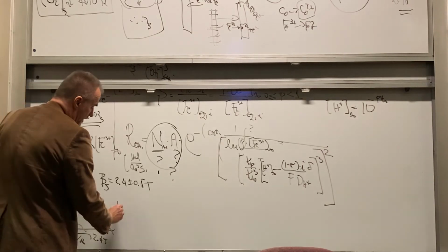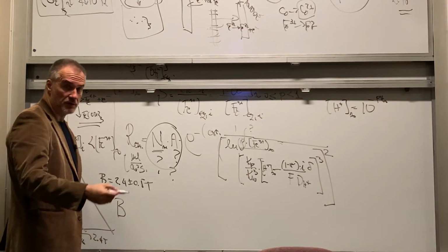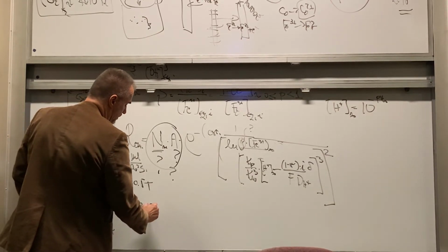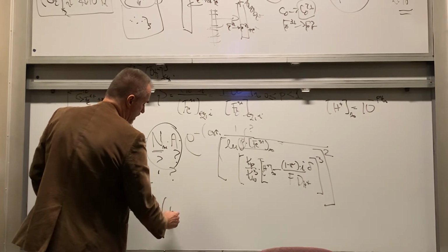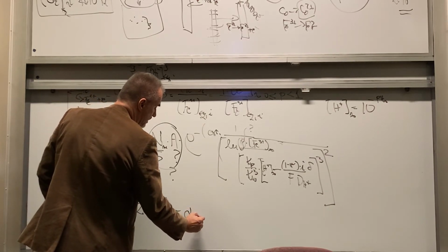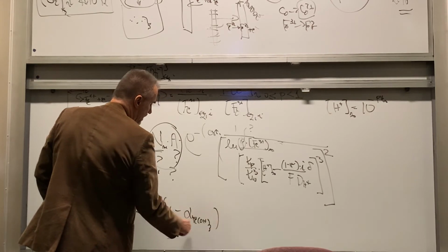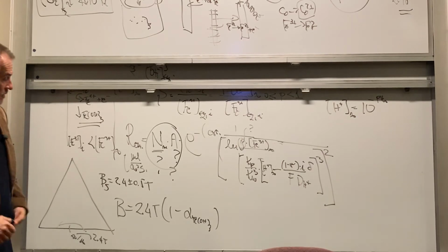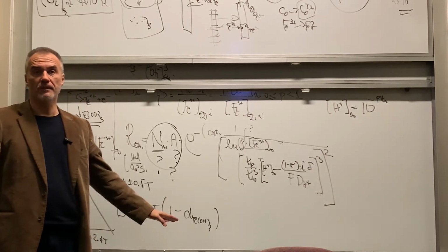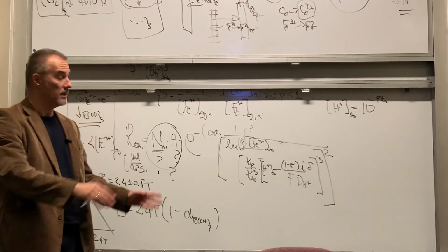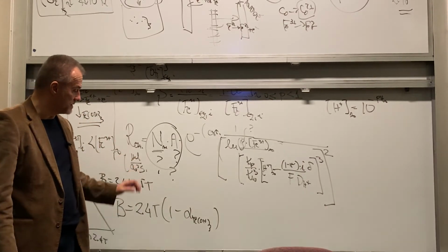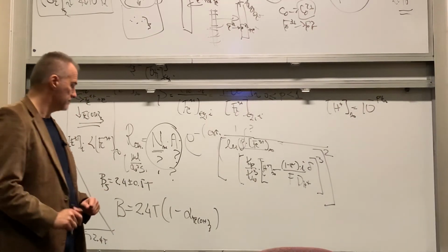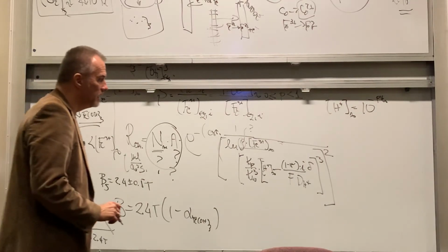Which means that the magnetic moment of my film, which I think is cobalt iron plus some oxide phase, will be basically 2.4 Tesla times 1 minus alpha iron 3 hydroxide. And iron 3 hydroxide is the volume fraction of this oxide phase. Now I have a rate, which is moles per centimeter squared per second, but I need volume fraction. How am I going to get the volume fraction? All right, so bear with me, I'll explain just in a moment.